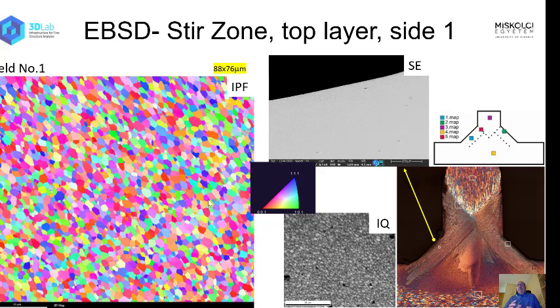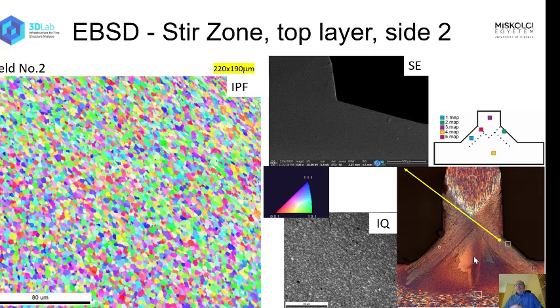The most fascinating thing was that the EBSD in the stir zone was extremely equiaxed. The grains were very fine and extremely the same size. That means equiaxed, that's another term. In spite of all the flow lines we see here, in reality, these are extremely good welds, very, very isotropic in all directions. That's the bottom line. Both sides of the weld show the same behavior.